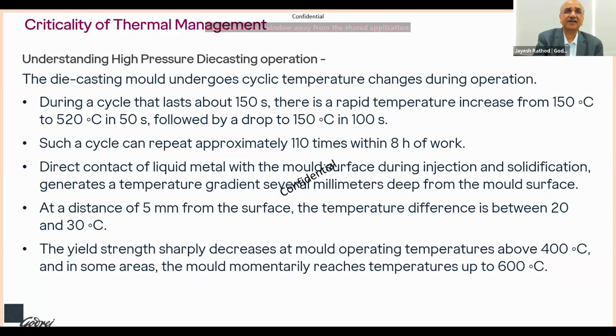If we try to understand how the high pressure die casting operation happens, in a shift, if 150 parts are being produced on average, the die goes through a thermal cycle ranging from 150 degrees centigrade to around 520, or sometimes it reaches 600 degrees centigrade, and the cycle time is hardly 150 seconds. Because of this huge temperature fluctuation, the condition of the die steel remains very challenging because it affects the yield strength of the tool steel. So this temperature gradient affects the life of the tool, and the casting which comes out of it is also getting affected.